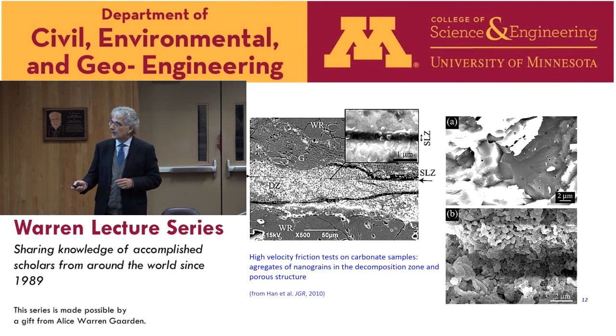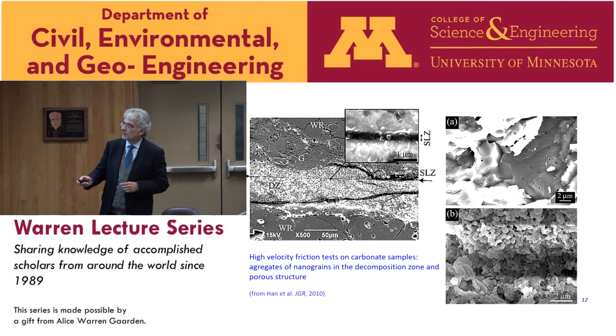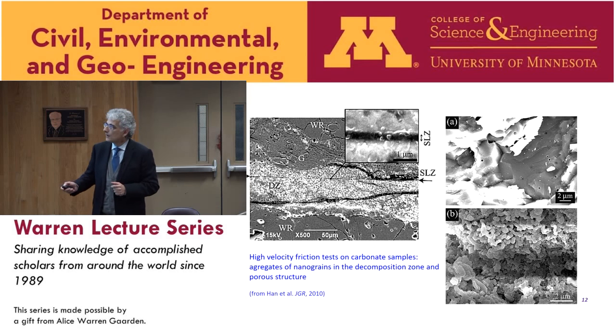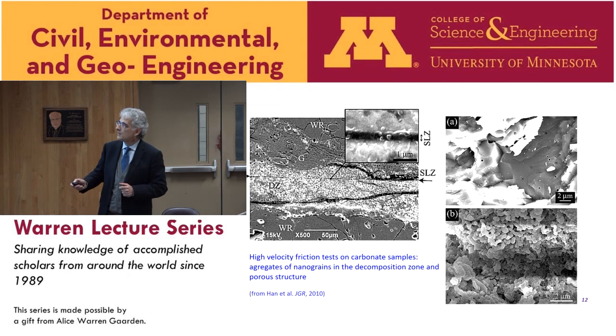This is an example taken from a paper on high-velocity friction tests on carbonate samples. And we see here, it's called DZ in this picture, the decomposition zone. We see the scale, 50 microns, so it's about 50 to 70 microns of this zone where decomposition of carbonates has occurred. We see this different microstructure, a more porous zone as compared to the wall. And yes, this is a zoom of this zone.